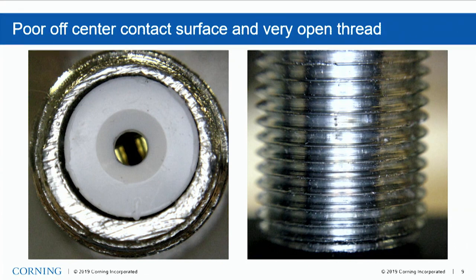This is one of the taps from the picture before. As you can see, this is an off-centered drill hole for the center pin. It's a very rough surface, and the threads over here are very open — there's not very much material left. If you over-torque it — and I'm not talking 100 inch-pounds, maybe 50 or 60 inch-pounds — it might break. It might just strip the threads.